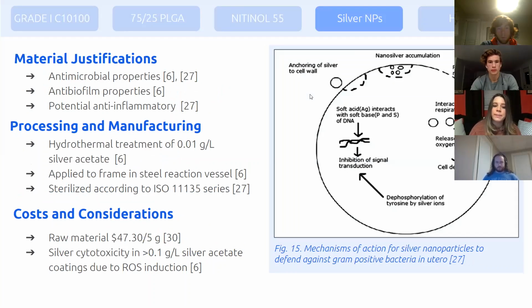Now, given the increased occurrences of upper and lower genital tract infections, our device seeks to create a frontline defense which can protect the patient until consulting their clinician. We plan to hydrothermally treat the nitinol frame in a steel thermal reaction vessel for silver acetate to deposit silver nanoparticles onto the frame. Once in utero, the silver nanoparticles will display antimicrobial and antibiofilm properties in a variety of ways, as shown in Figure 15. The primary mechanism of action is for the nanoparticles to anchor in and penetrate into the bacterial cell wall. And though the raw material is reasonably priced for the amount of silver acetate required, steel reaction vessels can cost upwards of thousands of dollars. Furthermore, the mechanisms for silver pathogen killing can also trigger a cytotoxic response. The amount of deposited silver must fall within a very specific range to meet anticipated outcomes while not causing significant side effects.